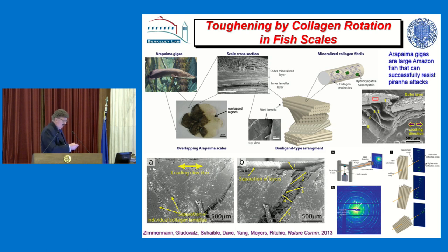We looked at this in particular in a fish called the Arapaima gigas, which is a fish in the Amazonian rivers, which survived for eons in the presence of piranha, which are of course known to be very aggressive and hard-biting fish. We actually took a piranha tooth and did a hardness indent by pushing it into the material. But you can see here that when we look at that lower level, which has got the resistance to fracture, the collagen is in a spiral staircase type arrangement. It reminds me of a Liberace spiral staircase. And it's got this twisted structure, called a Bouligand structure. These are not perfect Bouligands.